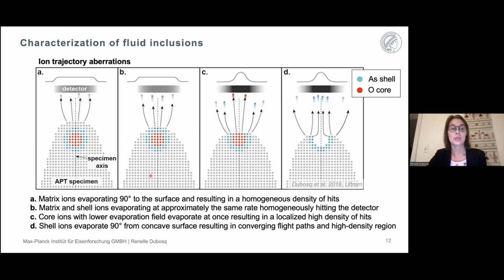In image B, we start to evaporate matrix and shell ions, and since they have a very similar evaporation field, they evaporate at approximately the same rate, and they hit the detector with a homogeneous distribution. So again, we still have this homogeneous density of hits. In image C here, we now expose the core of the core-shell particle, or of the fluid inclusion. Since these core ions have a significantly lower evaporation field, they evaporate at a very fast rate, almost at once. This results in a localized high density of hits on the detector, shown by this dark area. And since they evaporate at once, we don't have time to register their Z dimension for the 3D reconstruction, which is why it leads to these oblate or disc-like structures.